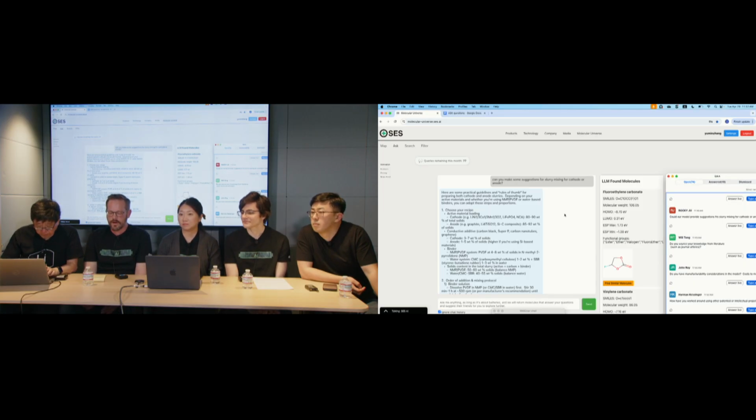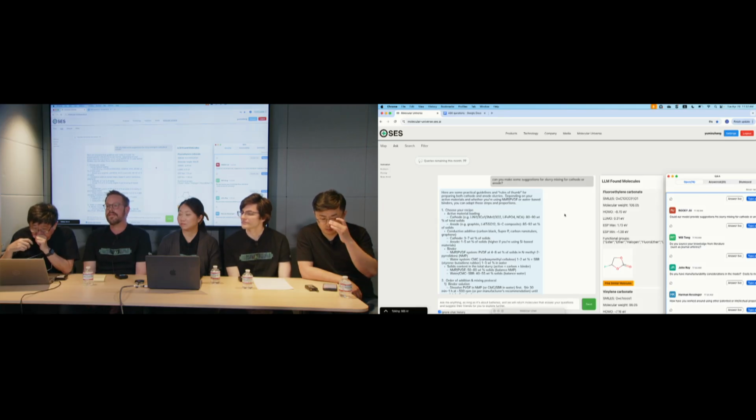So basically, we've parameterized these calculations to be mutually compatible across the entire data set and have vetted them for their accuracy in correctly ordering the experimentally measured stability of these solvent molecules in various kinds of testing regimes and data sets. And so we stand by the ability of the parameter sets we've used to render predictions that should correlate with what someone would measure in the lab. But of course, it is absolutely true that if someone were to run these calculations using different settings, the absolute values of those HOMO and LUMO numbers may, and indeed will, be different because they're a property of the exact basis set and functional that was used.